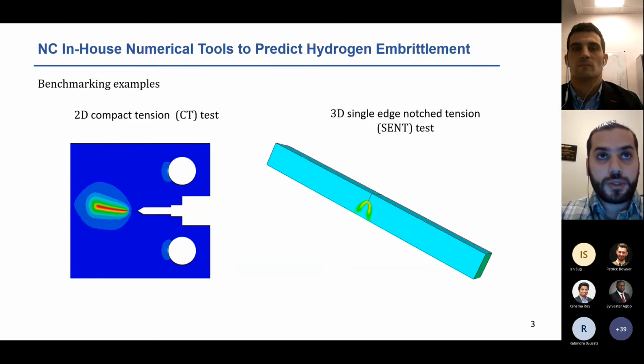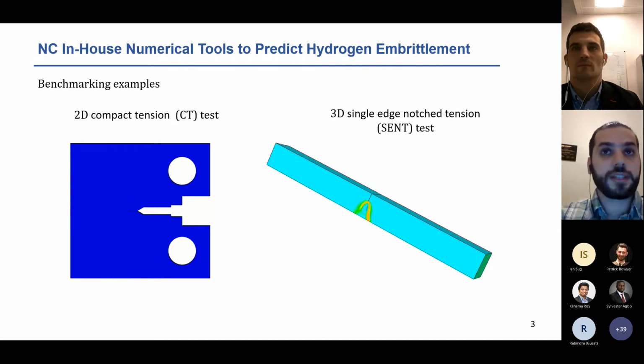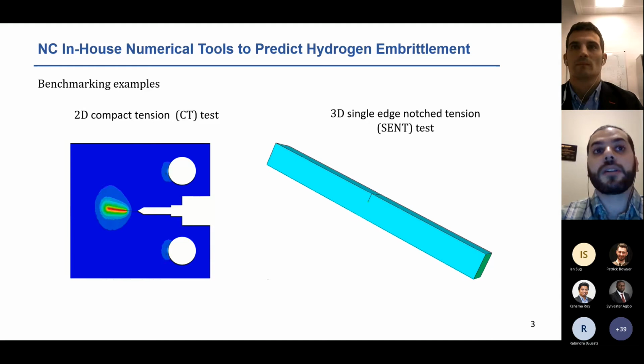This slide also shows two other benchmarking examples where the steel is exposed to hydrogen. The video on the left shows the damage initiation and evolution in a 2D compact tension or CT specimen, and the one on the right shows the damage in a single edge notched tension specimen or SENT specimen. Using our in-house numerical tool, we were able to predict hydrogen embrittlement in these examples.